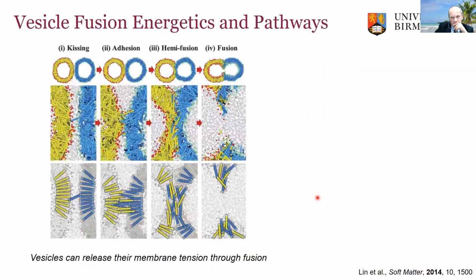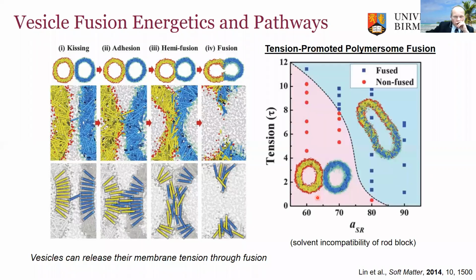So if we think about what might be happening, this is a Soft Matter paper from a number of years ago from another group that describes dissipative particle dynamics, and the simulations that they show that fusion basically occurs between vesicles simultaneously if the vesicles can adhere to one another and maintain close contact, and if there's sufficient membrane tension to overcome the energy barriers of fusion. They showed some really nice work on the tension required for that, and fusion helps release high membrane tension.